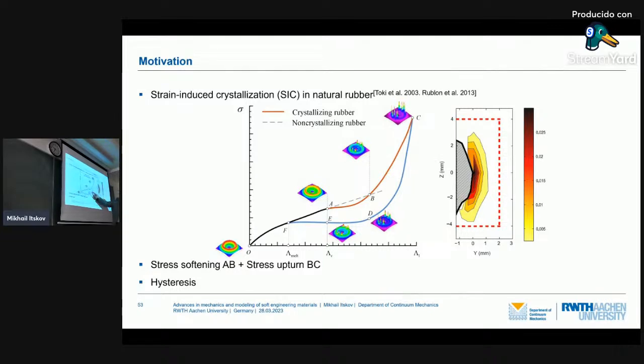crystallization appears at very high stretches. You see here these X-ray diffraction halos. By the way, it is a very expensive experiment, and there are only 2 devices in Germany where you can make these measurements. So it is ideal to use thermography in order to detect crystallization. We see that this crystallization begins at very high stretches, about 4. And such high stretches appear very seldom in rubber. But around the crack tip, we have concentration of strains, and very high strains can appear. Exactly here, the crystals can appear and retard or even stop, as I mentioned, the propagation of cracks.